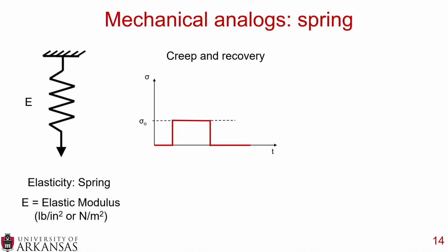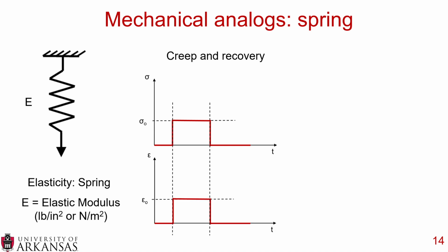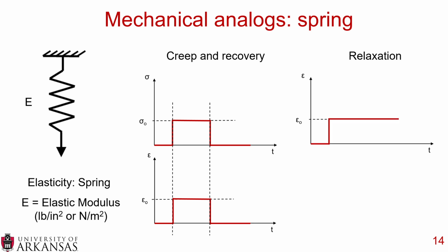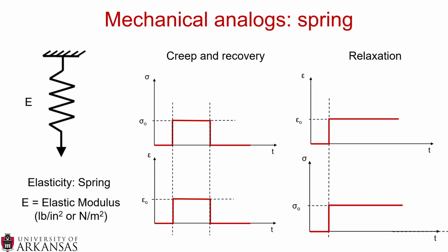And in creep and recovery tests, you apply some sort of constant stress, and then you take that stress off. And you measure the resulting strain, and when you take that stress off, the strain returns back to zero. So when you have a spring, the two curves look the same when we're talking about the creep and recovery. Now for the relaxation, it's a little different. You apply some sort of constant strain, and the resulting stress is also a constant.